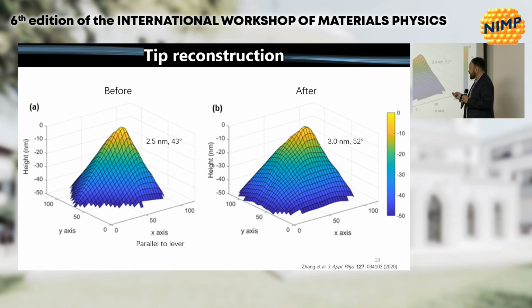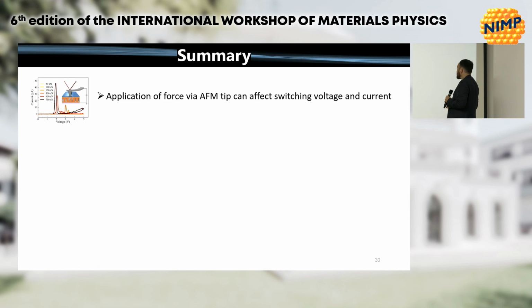Another striking thing, for me anyways, is that this is a reconstruction of the tip from the very beginning. And the only change that we saw in these tips was after the first scan or the first attempt, and after that it was very stable. So most of the deterioration happened very early on. We used basically 2 tips for all of the work here. One was for carving sharp structures, where this is just 2 or 3 nanometers, and the other one was a 50 nanometer tip apex for removing a lot of material. That one didn't change at all. This one changed only slightly. So even though the tips might be more expensive than other tips, they really can last quite a long time.